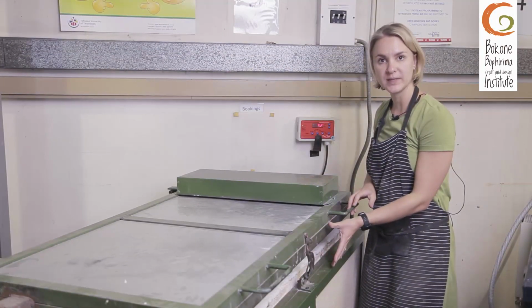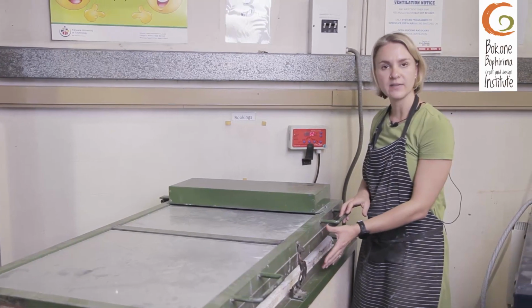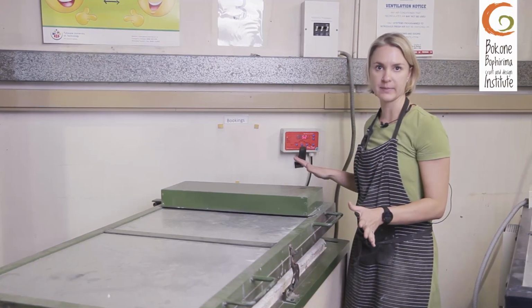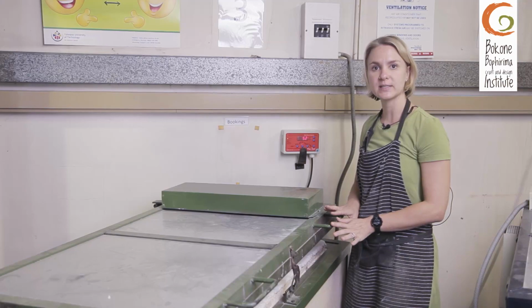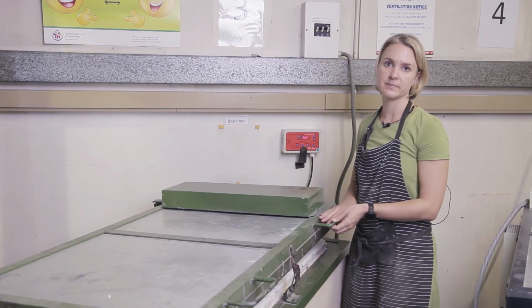I'm going to leave it open just a little bit, just to ensure that if any moisture is in the kiln, that it's able to escape. Once it's reached 100 degrees Celsius, I will close the kiln completely.